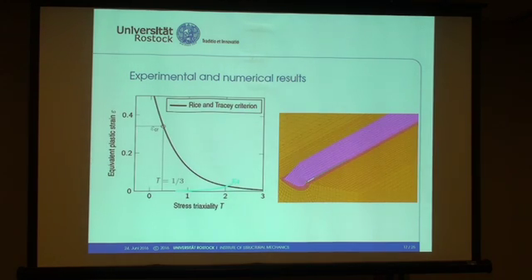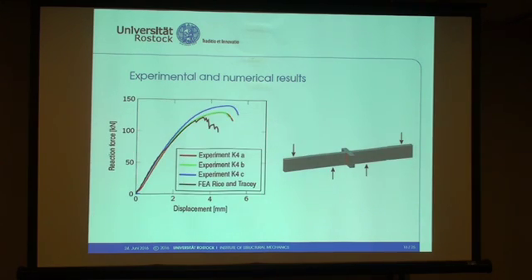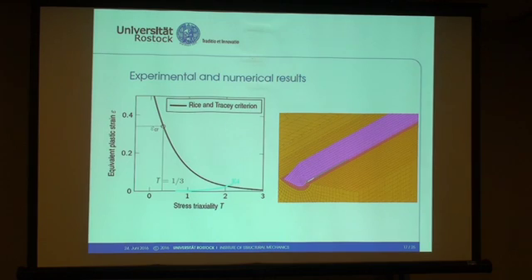Here you can see the crack initiation in the weld metal, highlighted with white elements. The yellow plate is the center plate of the specimen, and also the heat affected zone. And as I said, the location of crack initiation is here in the weld metal at the welding gap, and the crack growth with an increasing load goes from that side of the weld joint along the welding gap this way to the other end, and also crosswise through the weld metal.